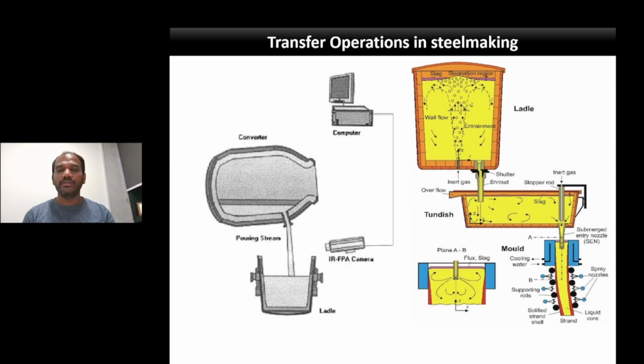Another transfer operation that takes place in the steel making process is during the continuous casting, where you can see the liquid steel will be transferred from ladle to tundish and then tundish to continuous casting mold. So the difference between these two transfer operations is one is taking place at the early stage of steel making, and the other, that is teeming, takes place at the later stage of steel making. In case of teeming, a mere entrainment of slag itself is very dangerous, because that is going to give you some exogenous inclusions in the steel products.